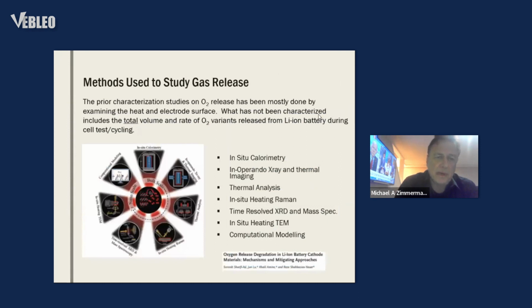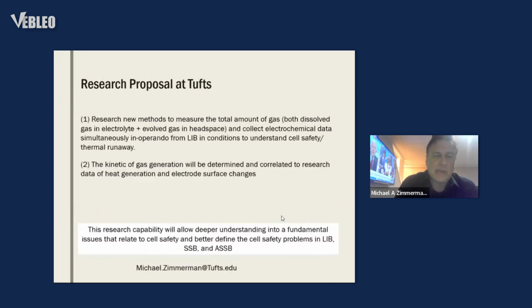There's been methods used. So as I mentioned, one of the root causes of thermal runaway has to do with bringing fuel to the fire, things like oxygen release. And I believe that this oxygen release is a major root cause of thermal runaway. It's been somewhat studied. This is from a review paper I found. It's been somewhat studied by in situ calorimetry, operando X-ray and thermal imaging, thermal analysis, time-resolved XRD, TEM, computational modeling. But there's things that have been lacking in this.